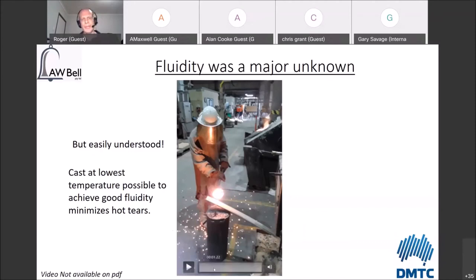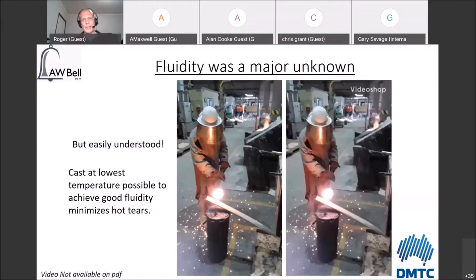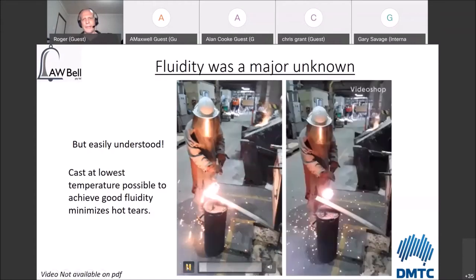That's what we're set up for here. That's actually a cinder pig from one of our furnaces with a bit of rebar on the top of it, and then we have the angle iron that's in here. As long as you don't move the angle iron, your results are comparable. There's nothing particularly quantitative about doing this, but it's very, very cheap and easy to do. It costs you nothing to set it up, and you get a good result. So I did video this, so you get some idea about what's being done.